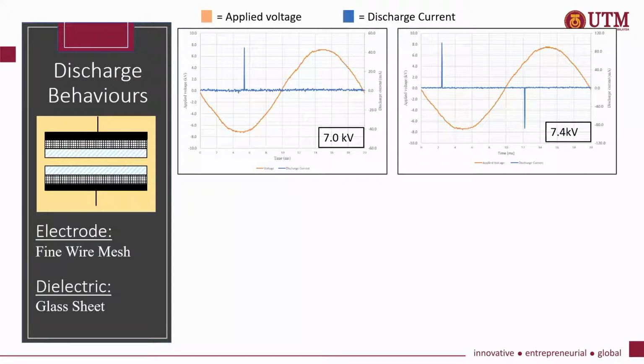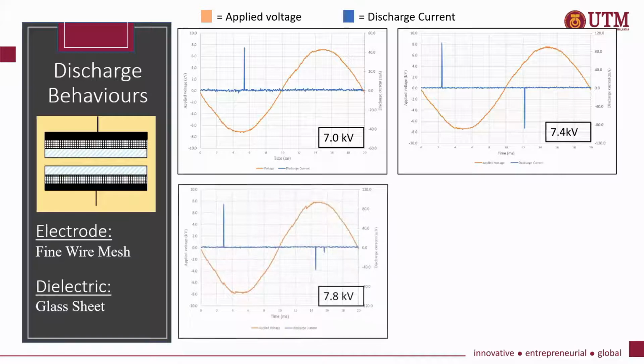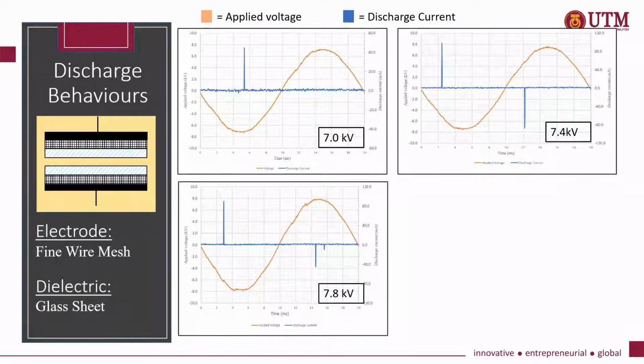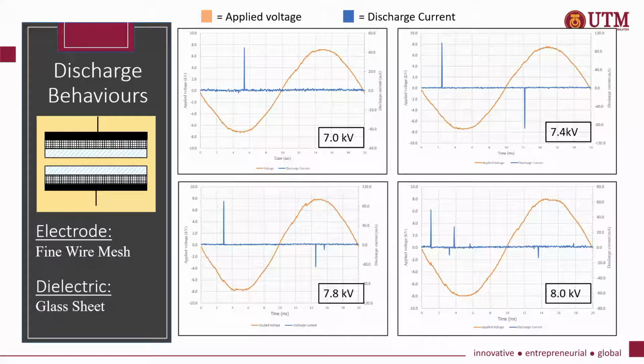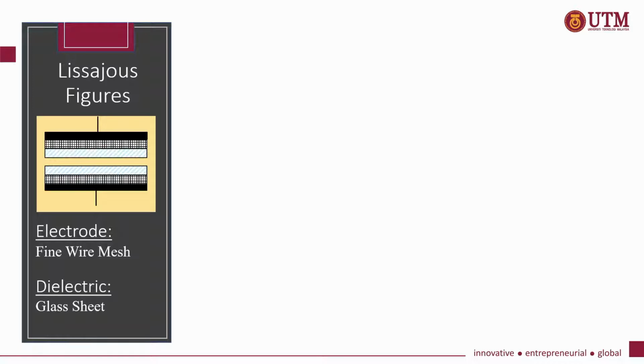However, when the voltage is further increased to 7.8 kV, the glow discharge has started to change into mixed glow filamentary discharge. And finally, it will become a pure filamentary glow discharge at 8 kV, where there are several current pulses in each half cycle of the input voltage. A voltage-charge Lissajous figure was obtained to verify the results obtained from the voltage discharge current waveform.